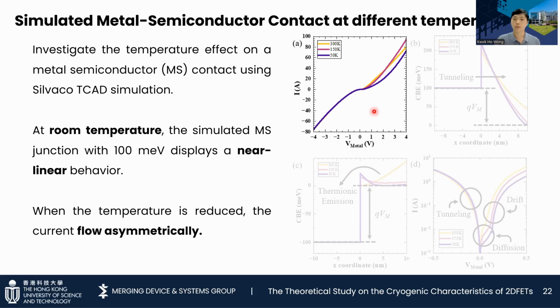The contact interface between the metal and the semiconductor film with MoS2 material properties is analyzed using Silvaco TCAD simulations. In order to match the experimental conditions, the metal-to-semiconductor barrier is intentionally selected as 100 meV. At room temperature, the simulator displays the linear output characteristics, which is consistent with the experimental data on the previous slides.